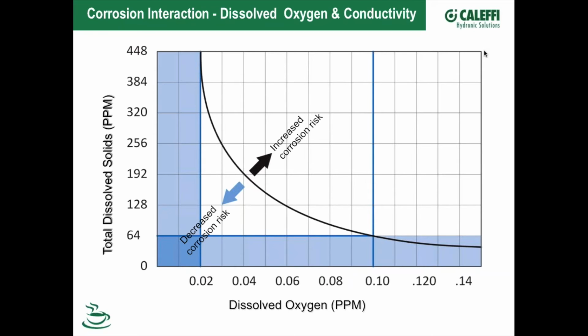But the other thing is that oxygen can get into a system, and even with barrier tubing, oxygen gets through at a low rate, but over a period of time, maybe 5 or 10 years, especially on the higher temperature systems, you still have oxygen getting through the wall of that tubing. The numbers that you look at when we show you our tester here will indicate if that's happening. If you get a lot of oxygen in the system, it's going to show up in a number. Then you either have to put an oxygen scavenger in there to treat that, or keep it out. It's coming in through an air vent or a pump seal or something like that.